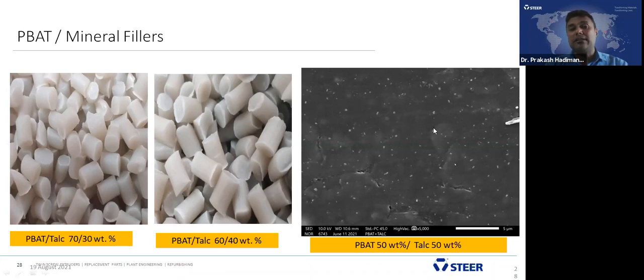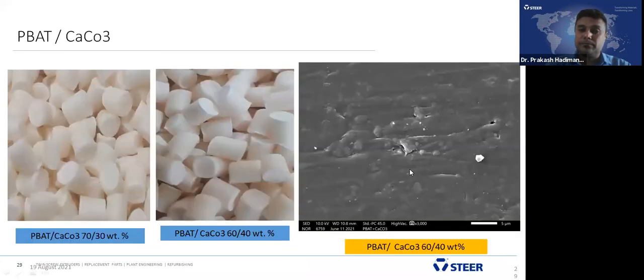You see the morphology study, it gives us the distribution of talc. These are the white particles you observe. This talc is completely distributed and dispersed in the PBAT at 50 and 50% weight. And the PBAT and calcium carbonate, here also similar. The dispersion was good. We had a smooth surface, good pellets at 30 and 40%, but we observed slightly bigger